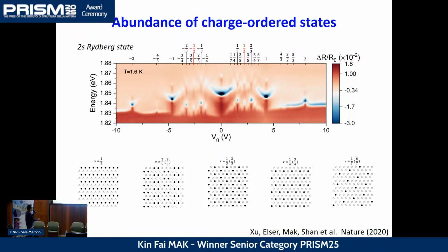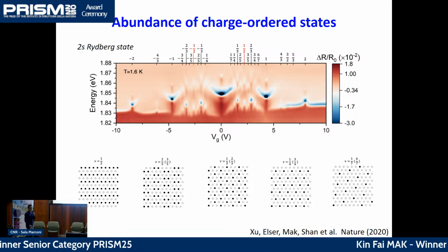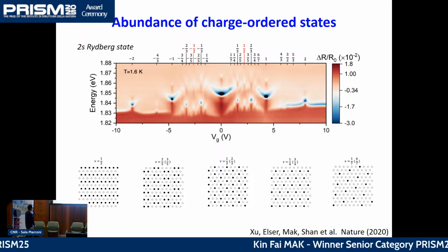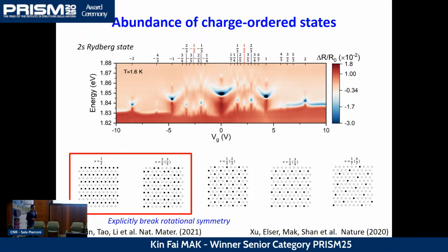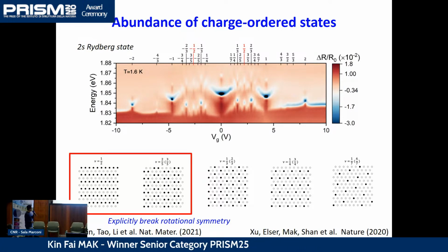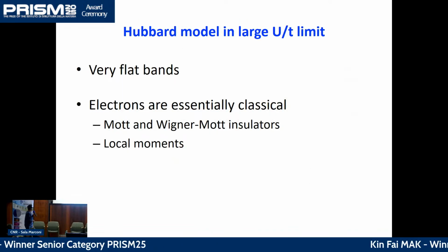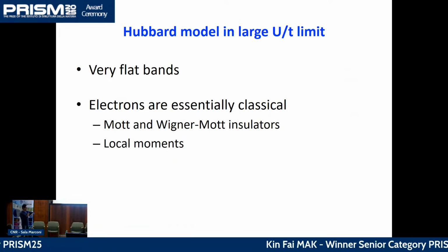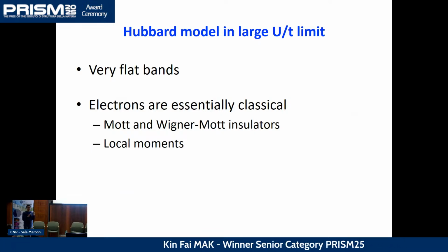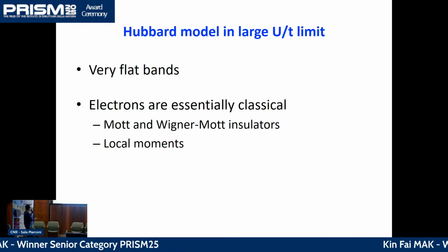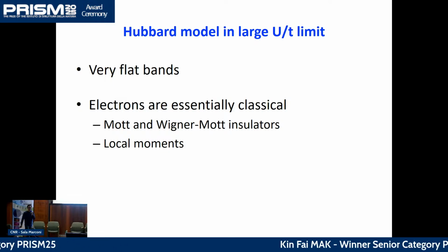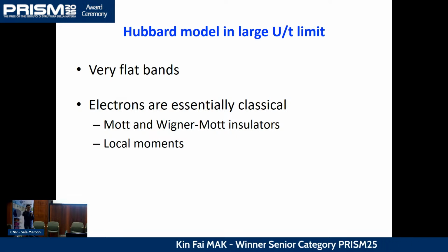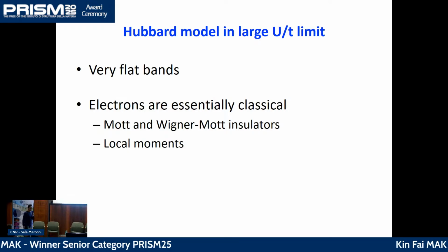For instance, the electrons at 2/3 would form a honeycomb lattice structure. At 1/2, they would spontaneously form stripes, breaking the rotational symmetry of the crystal, which can also be verified by an optical birefringence experiment. But I will skip this part as well. Okay, so what I have been telling you is the limit of very large U over T. In this case, the electrons have very little kinetic energy, and the bands are really, really flat. In some sense, the electrons are essentially classical objects, just particles carrying a charge. That's why it's a very good platform to study the Mott insulators and the Wigner crystals.